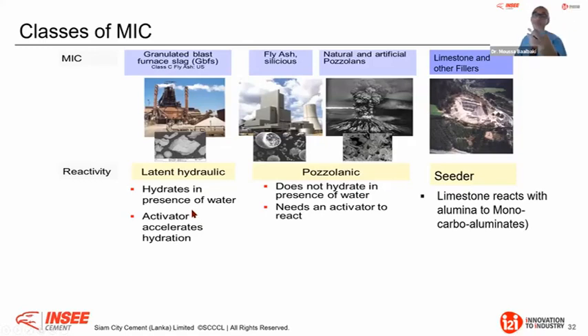For example, a byproduct from the hydration reaction of clinker is calcium hydroxide. Now, you have two other products called pozzolanic materials. And for those pozzolanic materials, you have the technical one, a byproduct like fly ash, coming from a power plant. We have it in Sri Lanka, in Norochcholai, for example. And those fly ash do not hydrate in presence of water. Therefore, they are inert. If I use them with water, they are inert. Therefore, they need activators.